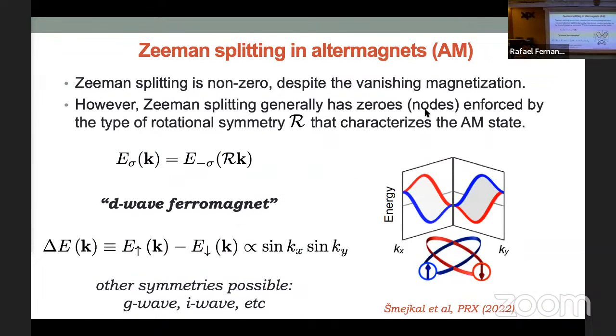Again, I don't have spin-orbit coupling. Now, because of my rotation, spin up and spin down are related as long as I apply this rotation on my momentum. But generally, k and the rotation of k are different. So I'm going to get the spin splitting, even though I have no spin-orbit coupling, even though I don't have a magnetization. But there are some directions that are invariant under the rotation, and that will give me nodes. So generically, what I'm going to find is that my spin splitting will be modulated. So you could think of this as a d-wave ferromagnet.